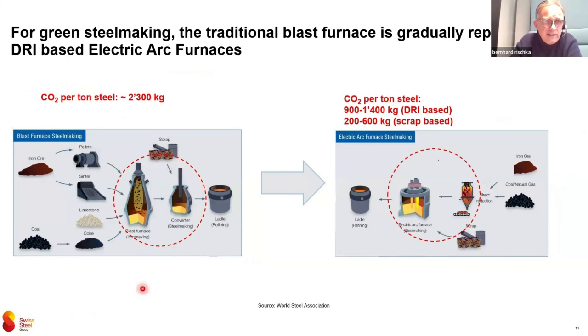Here on the left side, we have the major part of steel making. In the center is the blast furnace. What goes into the blast furnace is iron ore, coal, and limestone. Coal is first baked into coke. And that's a problem. How much coke do we need? A modern blast furnace has approximately 330 kilograms of coke per ton of hot metal. But you also see less efficient furnaces with 700 and 800 kilograms of coke.